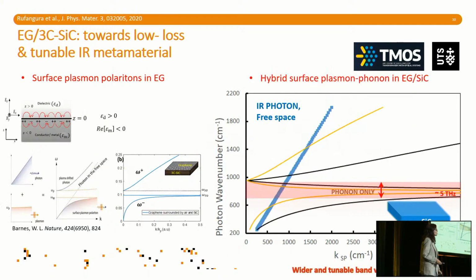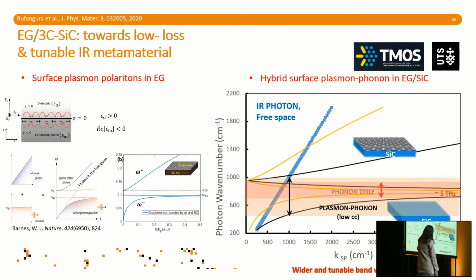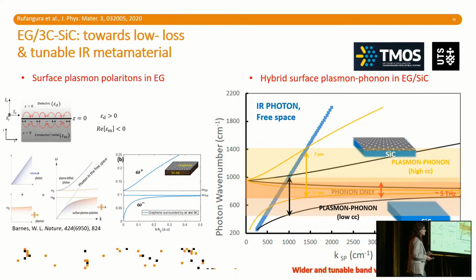However, that's where the graphene comes in. What happens is that you can actually hybridize the plasmon from the graphene and the surface phonon from the silicon carbide. And once you have that, and this is just a back of the envelope calculation to give you some idea of the ballpark, you can extend the responsivity range, not only extend it, but also tune it by tuning the carrier concentration in the graphene. And this is extremely interesting because of tunability, of course, that's the holy grail, but also the fact that you can extend that responsivity range beyond just the range of the silicon carbide. And this is basically the point we're working on.